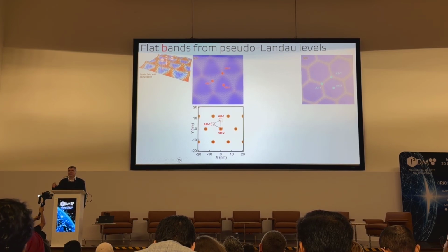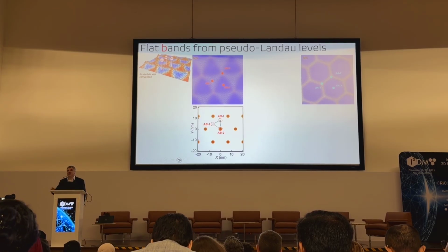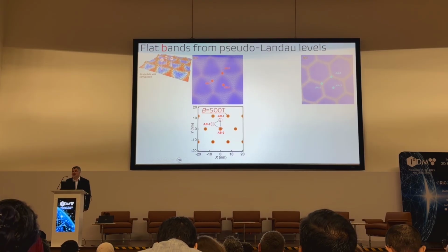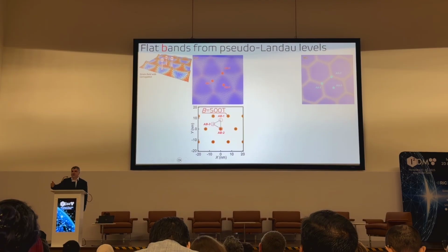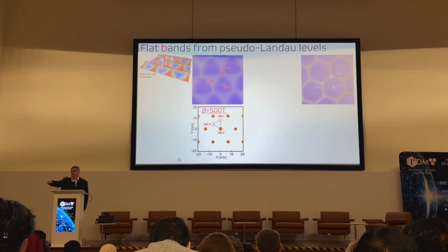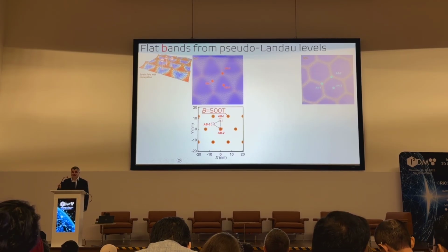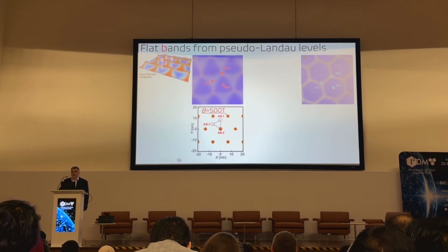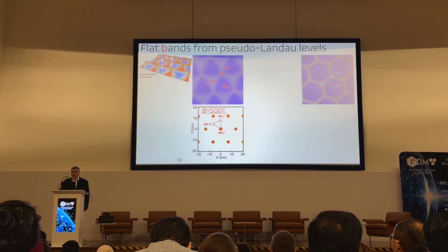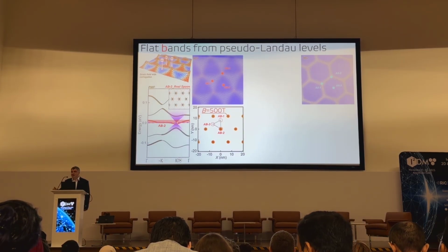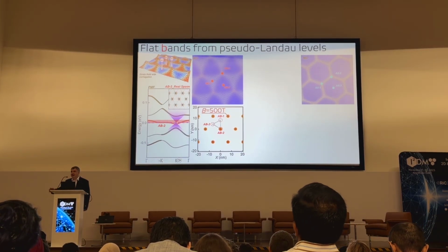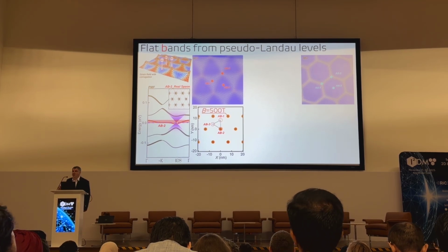So it looks like your sample is now pierced with magnetic pipes, and there is a magnetic field inside of those. It's not a real magnetic field, right? It is coming from strain, so electrons now have to move in a curved space. So it's topological in a sense, but the magnetic field inside of those pipes can be very high, like hundreds of Tesla.